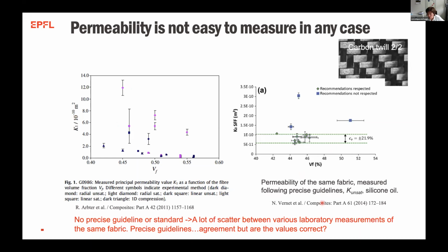Now, of course, second round robin, we took the permeability, same fabric, we gave precise guidelines. So it was an unsaturated permeability measured using silicone oil with given geometry and so on. And here you see, okay, a bunch of guys did not follow the recommendations. But the guys who followed the recommendation, we were much, much closer. And we have a value of permeability here that everybody more or less agrees with, about 21% variability, which is not negligible, but better than an order of magnitude.